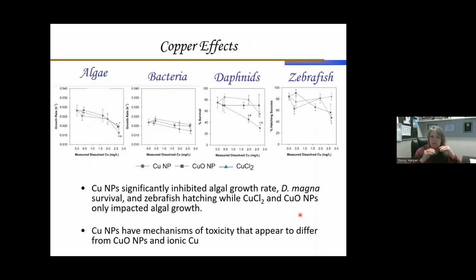When they're in these small scale microcosms, what we see is that copper here is the dark one. It's always the lowest line on the graphs. Copper significantly inhibited algal growth and Daphnia survival and zebrafish hatching. But copper chloride and copper oxide nanoparticles only impacted algal growth, and in a very similar fashion to the copper. So this means that the copper nanoparticles potentially have mechanisms of toxicity that are different than the ionic form or the oxidized form.